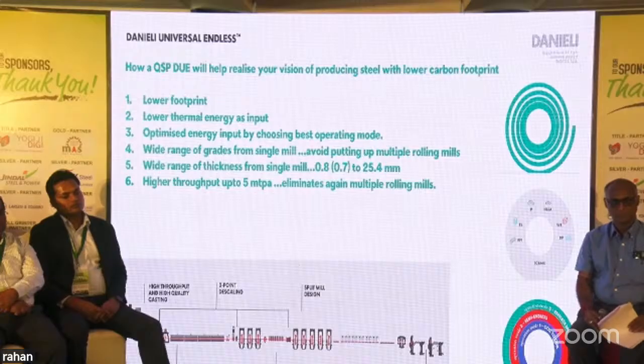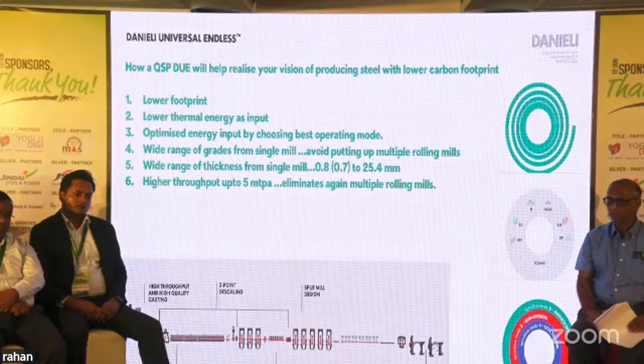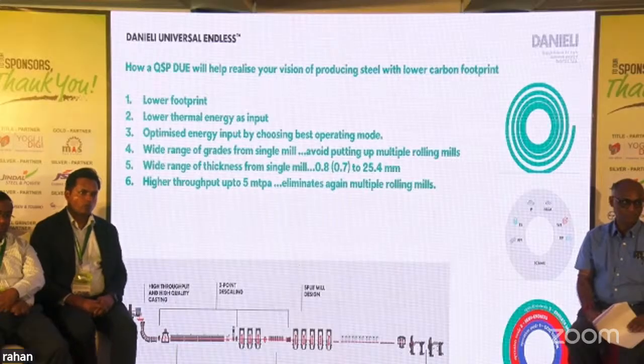Now, how? Lower footprint. This is a typical layout. What you can see is that from the caster till the down coiler, it is around 380 meters. A typical conventional semi-continuous hot strip mill will require around 400 meters. So this is where one of the advantages comes. The layout is very small, so the carbon footprint is less. Then the lower thermal energy as the input. As I mentioned, the input of the slabs at the tunnel furnace is around 900 to 1000 already.